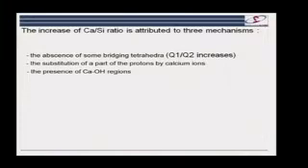Well, there's a lot of debate about that, but I think most people would agree that what we have is probably some regions that are like calcium hydroxide. What does that mean? It basically means you've got this sheet and you've got no silicates on it, because that is the calcium hydroxide structure. And it's all these missing tetrahedra, missing bits of silicate chain, which mean you have a disordered structure of CSH as opposed to the well-ordered structure of tobermorite.